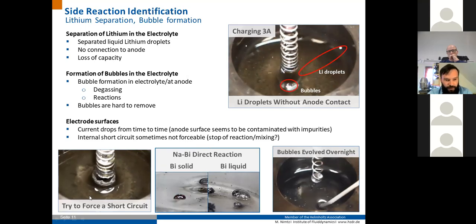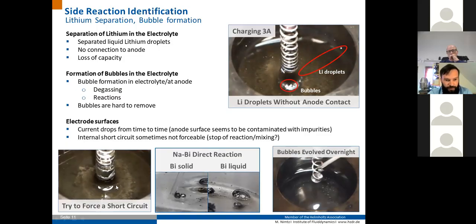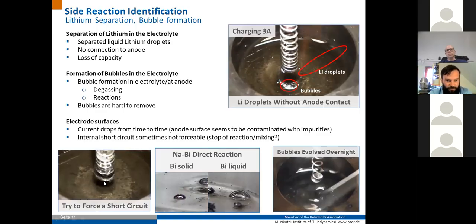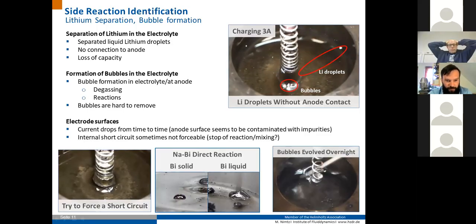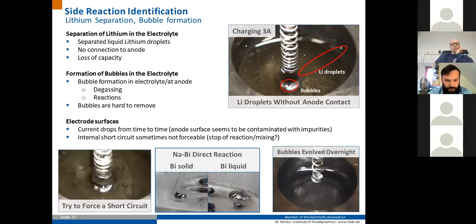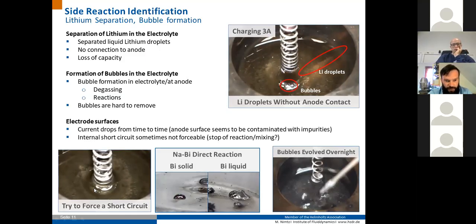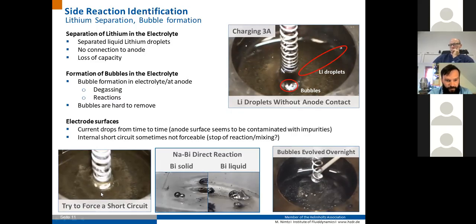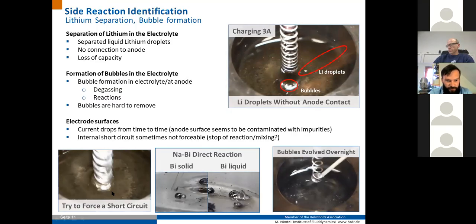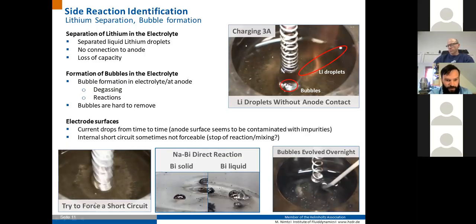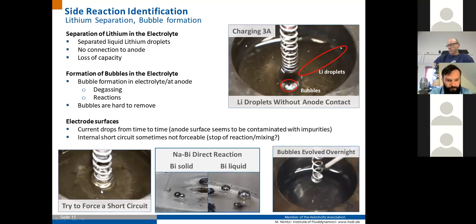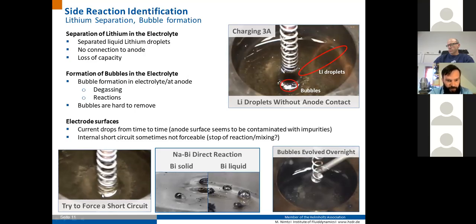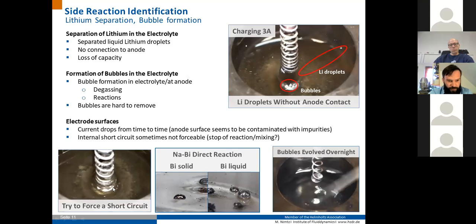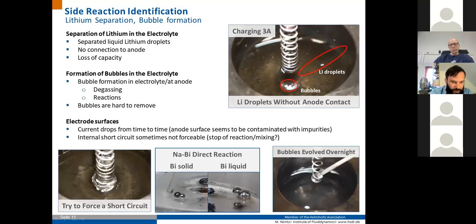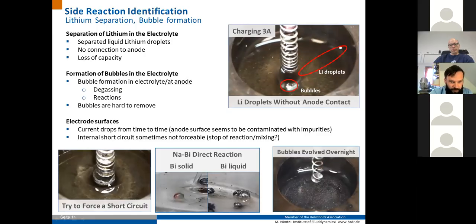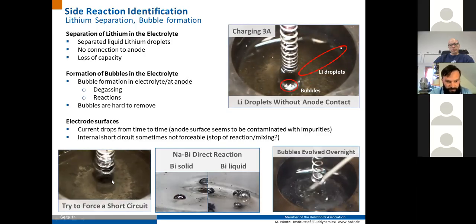also something you would not expect is, for example, from time to time we wanted to test short circuit behavior. Short circuit means both electrodes touching each other directly, and as you can see here, this try to force a short circuit by sticking the whole rod and the electrode inside the bismuth electrode did not work here due to surface forces. It was not possible to have a reaction between the two electrodes in the cell itself.